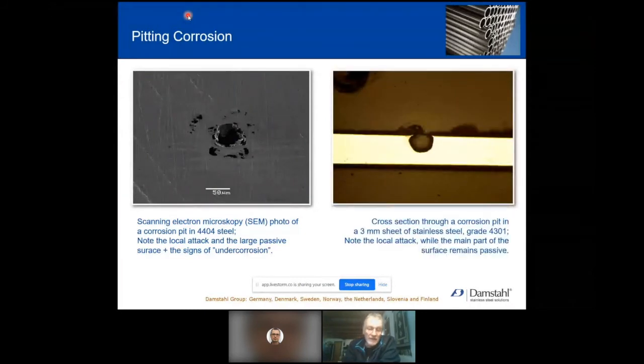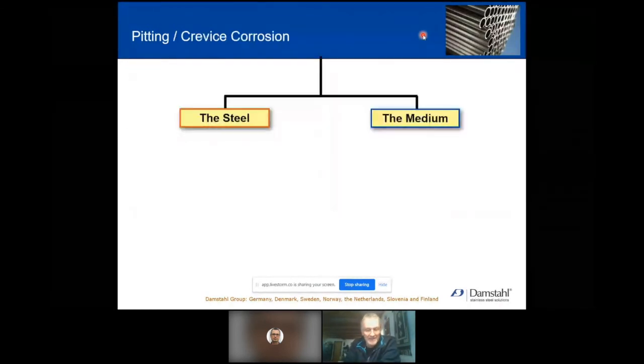Same here. It could be the same example. It's not from a practical example. It's from a water tank. This is a 3 millimeter different steel grade, 4301, but it's very easy to see how local the attack is. So this is really a question of avoiding the attack points for these local attacks.